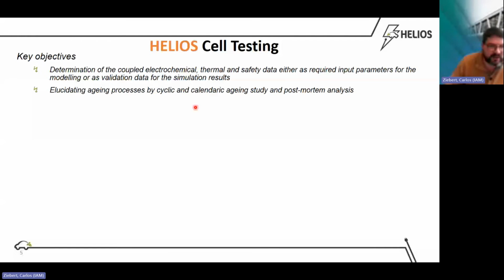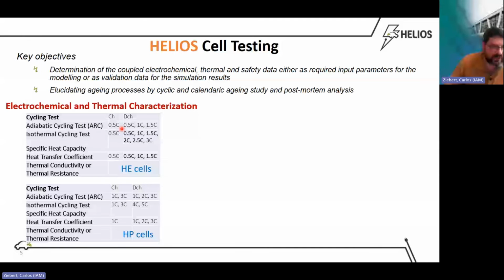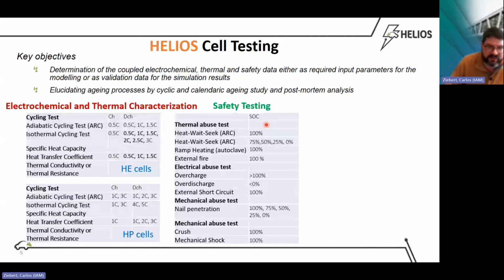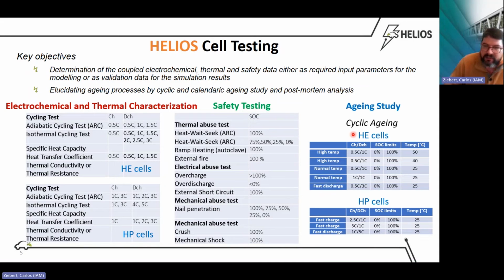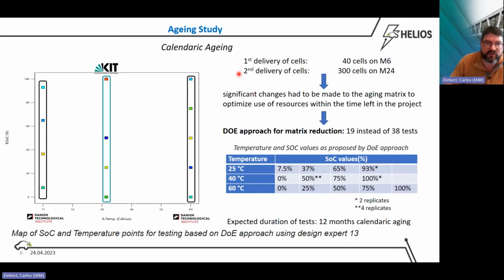So we have here the electrochemical and thermal characterization. We are, of course, doing different cycling tests, either in the temperature chambers or also in an accelerating rate calorimeter, both for the high energy and the high power cells. We are doing safety testing in accelerating rate calorimeters on cell level, electrical abuse, mechanical abuse tests. And we have matrices for the cyclic aging of the high energy and the high power cells, and of course also of the calendaric aging.